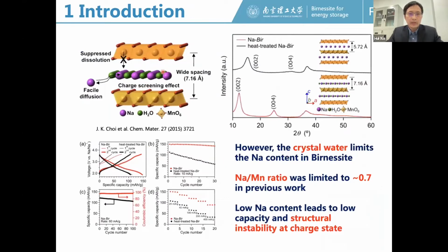And the Birnessite structure has some advantages. So first, it can reduce the charge screening effect. And also it can help improve the sodium ion diffusion in the interlayer. When we compare layered structures with and without crystal water, we can find that the Birnessite structure can have a larger specific capacity and improved cycle performance.